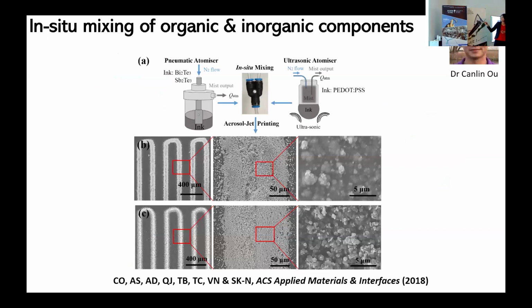But my student, Canlin, also showed that you could mix, for instance, an organic conductor, which a lot of you here will probably recognize, PEDOT:PSS, and an inorganic component. In this case, we use bismuth telluride or antimony telluride, which we've grown ourselves using solvothermal synthesis. We make an ink and deposit these two together to make a composite. And what Canlin was doing at the time was looking at the thermoelectric properties of these composites.